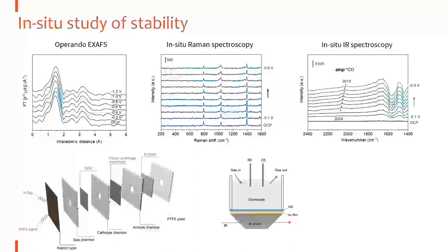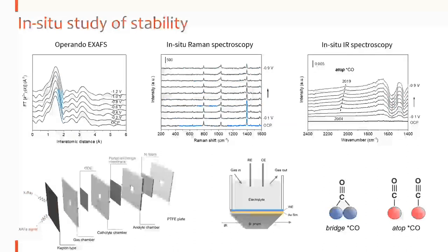We also provide further evidence using in situ infrared spectroscopy. This is kind of indirect evidence, so let me explain. Here, at around 2000 wavenumbers, we observe a peak, which is ascribed to the atop CO. If we know the CO adsorption on metals or any other substrate, usually CO has two different types of adsorption configuration. One is the bridge CO, another is the top CO. The bridge CO requires the CO to be bound by two atoms, and the top CO means that CO is only bound on one atom.